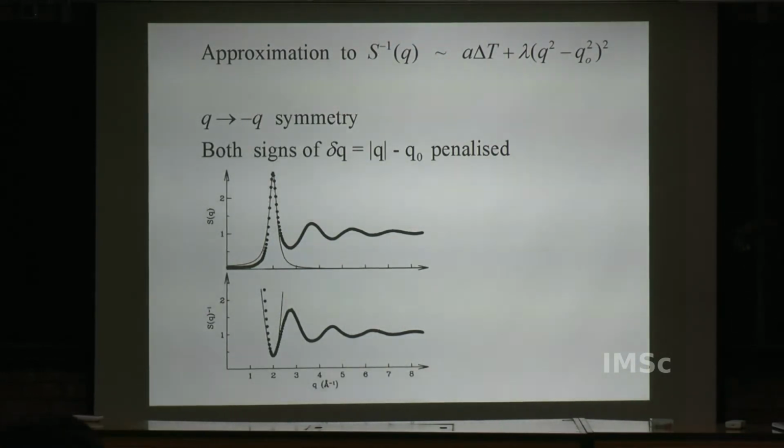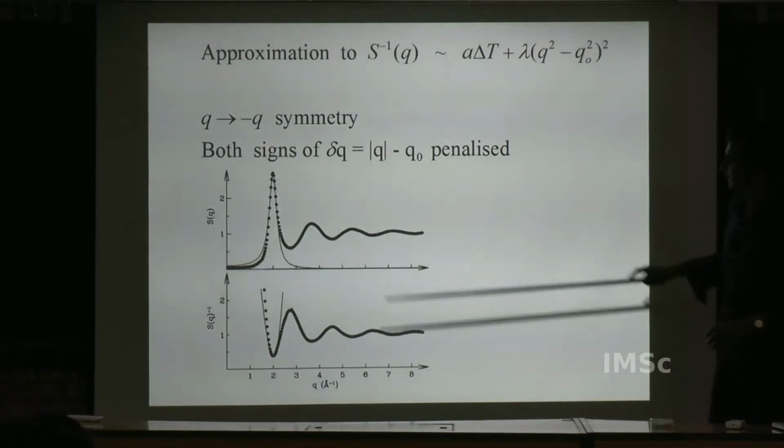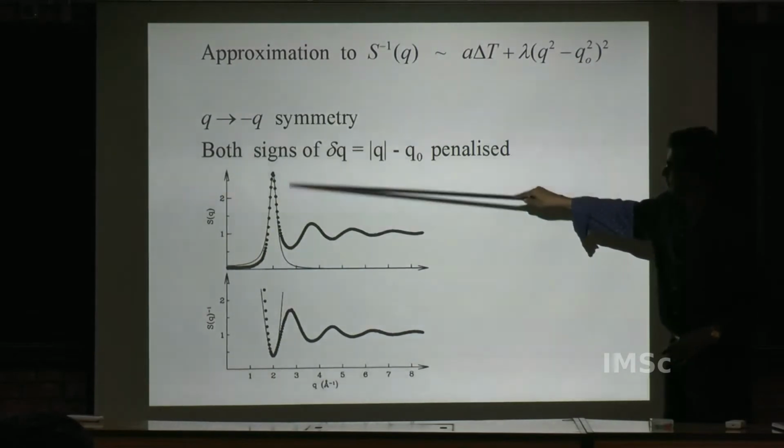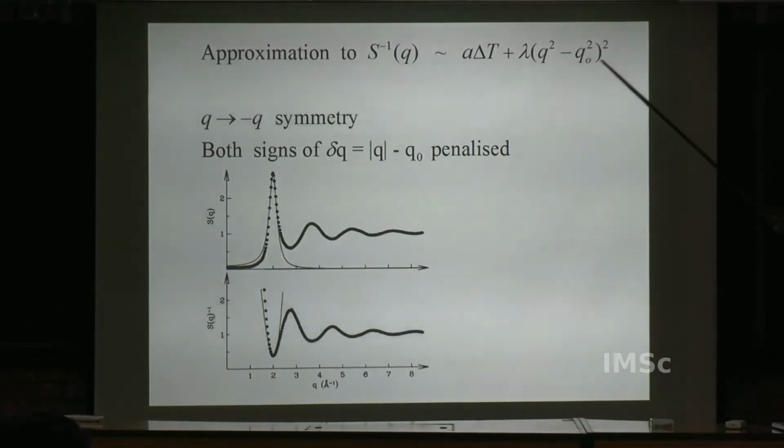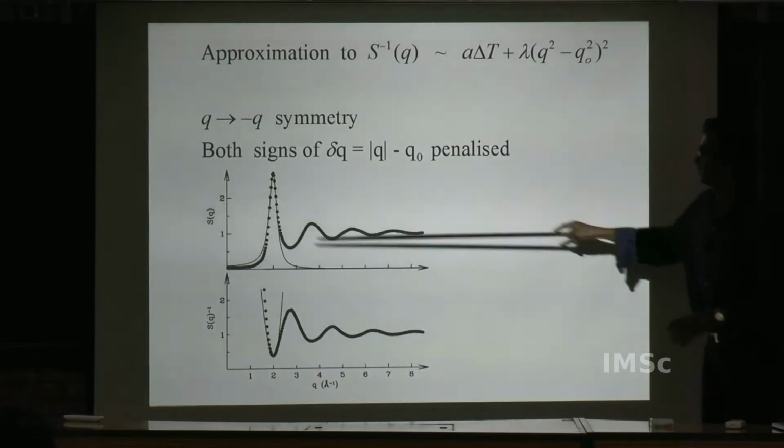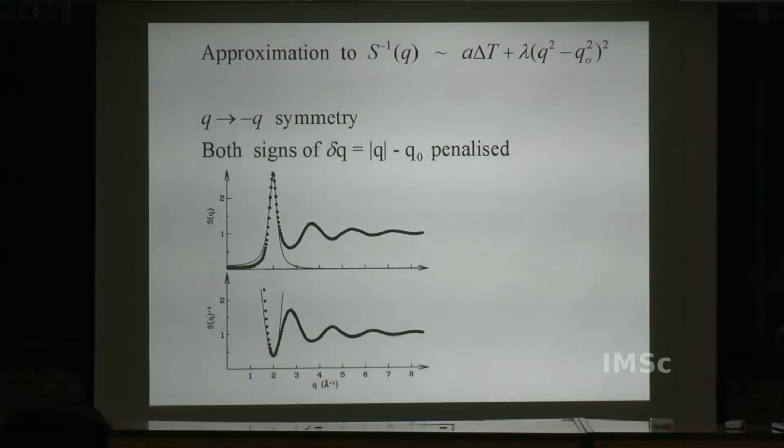Now in this crystal phase field theory, you are just putting an approximation, that is, you are just approximating the first peak using this function, and you are forgetting about these ripples. So you are capturing some bit of solid like information, but not all the details, and that is the reason why it will not give you all the correct solid liquid transition characteristics.